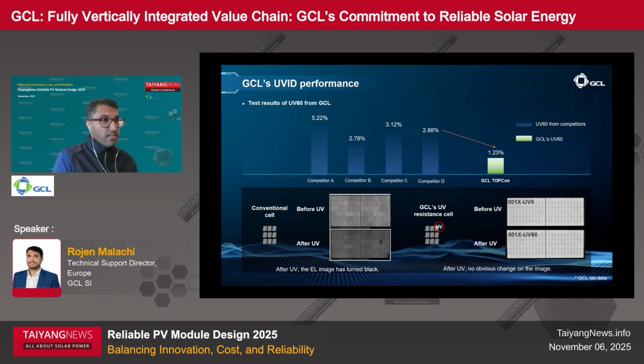Our enhanced passivation stack and process control limit UVID to around 1.2% for exposure of UVID 60 with controlled recovery behavior. On the bottom side, you can also see the differences in EL images for GCL's UV resistant cells compared to conventional cells after UV exposure.